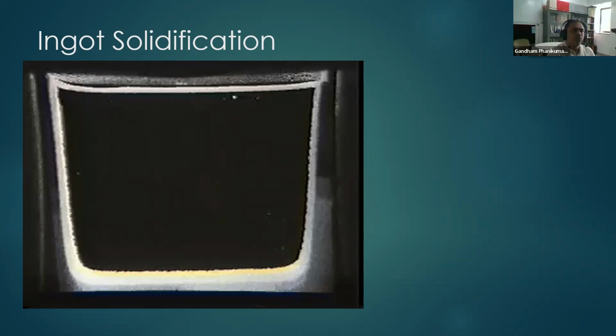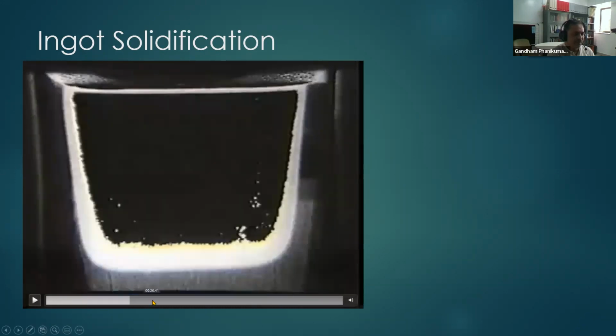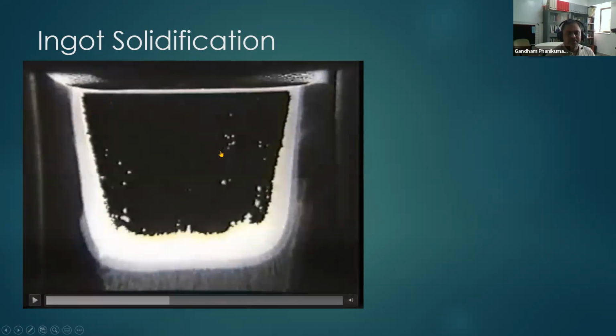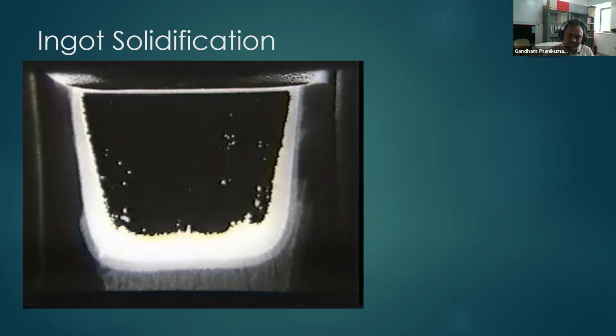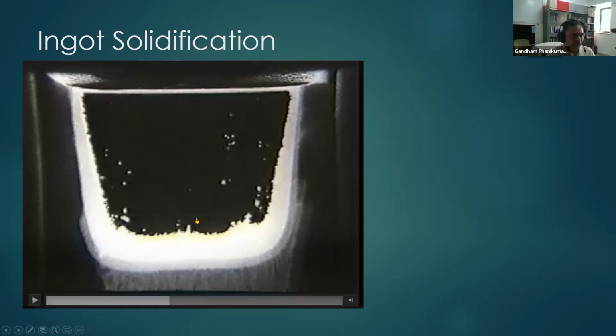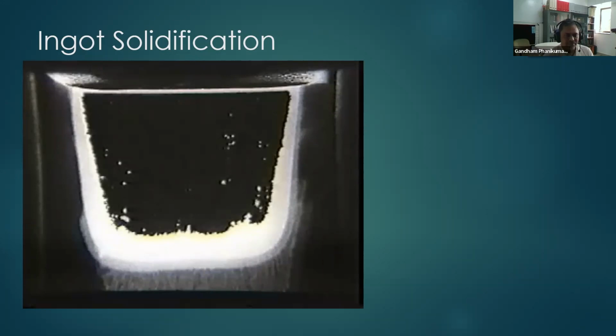Yes, it is possible. So this motion of the liquid is predominantly, in the case of ingot casting, due to what is called buoyancy convection. And in the case of a laser molten pool, such as in additive manufacturing, it will be predominantly due to Marangoni convection. Marangoni convection is surface tension driven convection. So here, if the laser is heated here and this is the melt pool, the temperature is high here and it's low here. And that difference is what is going to cause a surface tension driven flow called Marangoni convection. And today we can simulate those convective patterns, and we can also predict how the solid is going to detach and do its circular motion inside the pool.